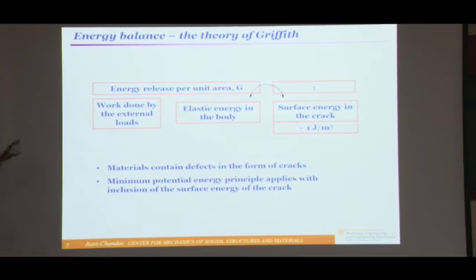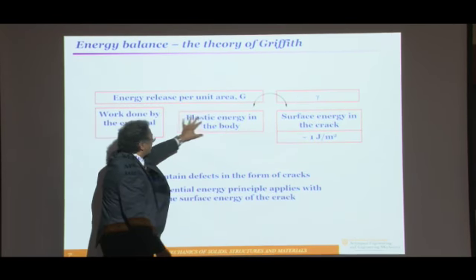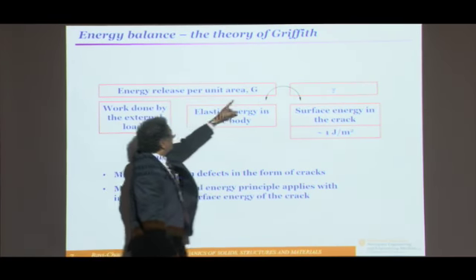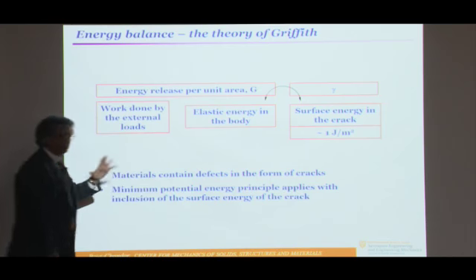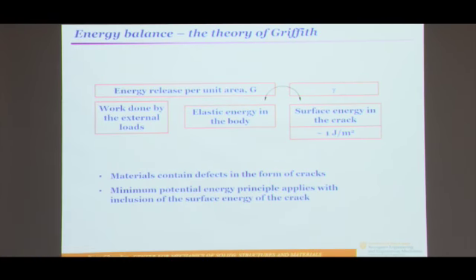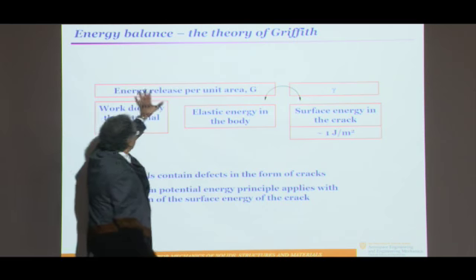The surface energy, let's label as gamma. So then we have a condition for failure, which says that if the elastic energy that is recoverable from the mechanical part of the system, in fact, this becomes, in addition to creating a free surface, you're always adding additional energy of the new surface that you create. Exactly the surface energy for this.